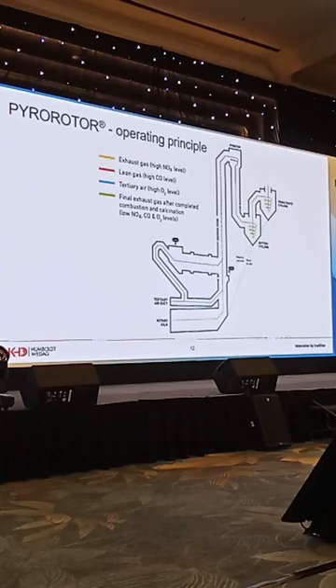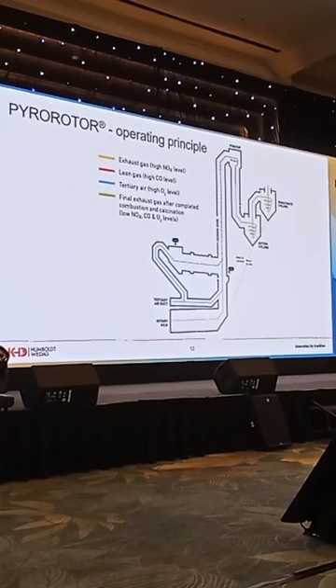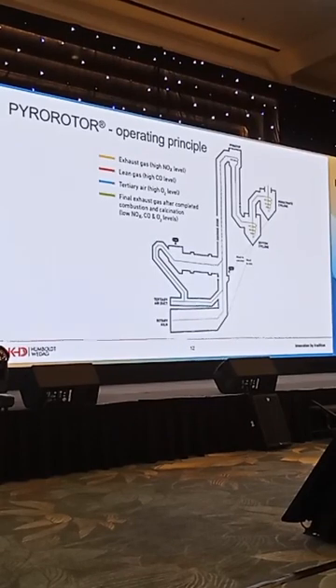And then you are directly feeding the alternative fuels into this system and burning the material inside the pyrorotor. Because of the high amount of fuel and pretty low amount of combustion air, we are creating a CO-rich environment inside the pyrorotor, and the gases then pass through the pyrorotor to the calciner, mixing with the air which is already coming from the rotary kiln.